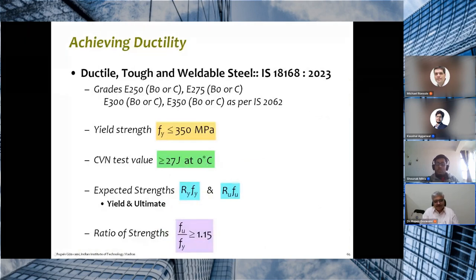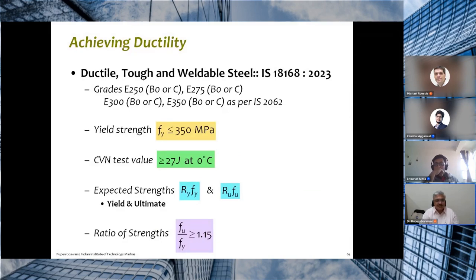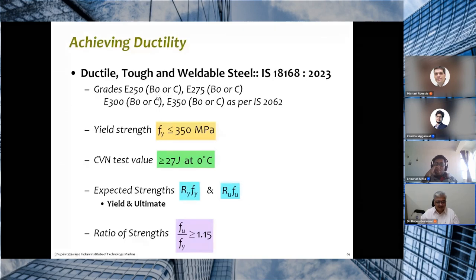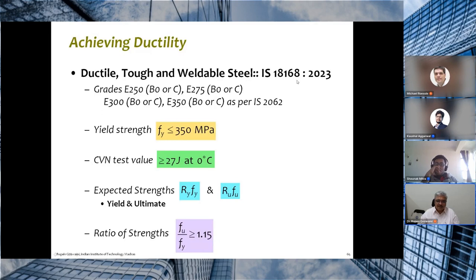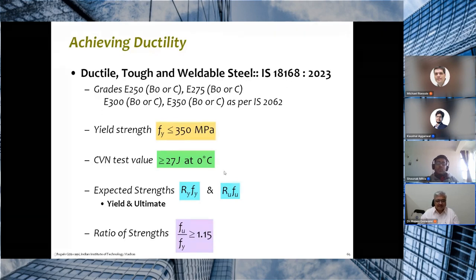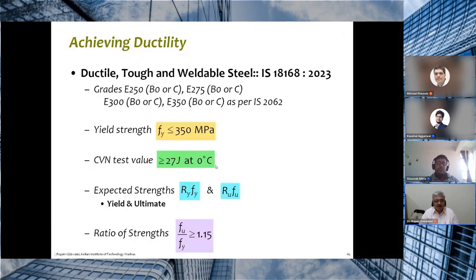Along with ductility, we also need two more additional properties to be guaranteed. One is toughness, which is essentially the amount of energy that the material can absorb before finally failing or fracturing. This is where we generally use the CVN value. If you go to IS 2062, you will see different grades of materials. For instance, E250 means 250 MPa in strength. But then there are A, BR, B0, and C. These are the four categories of steel for the same grade, and what is permitted for seismic application is only B0 and C. Essentially, it requires a particular CVN test value at 0 degree centigrade, and so on and so forth.